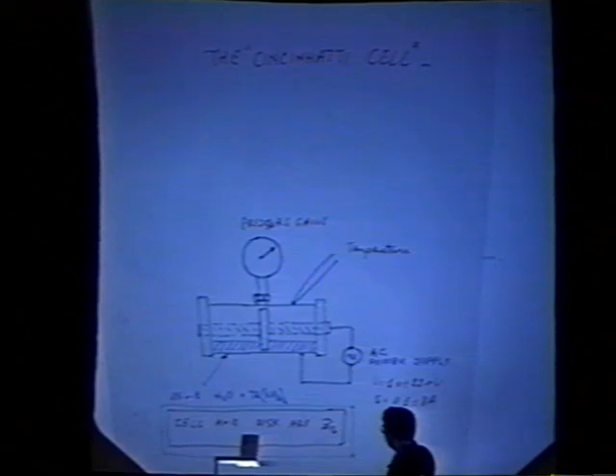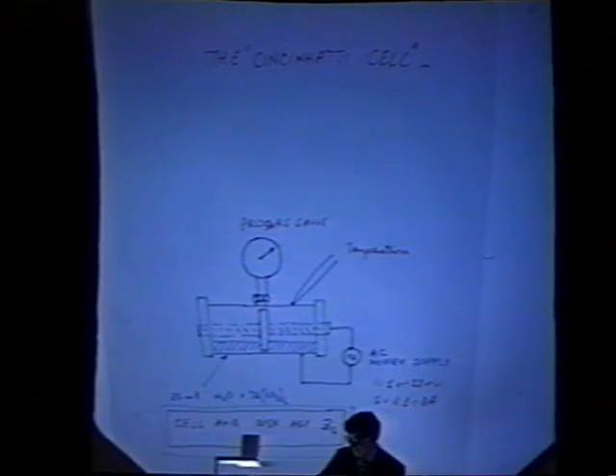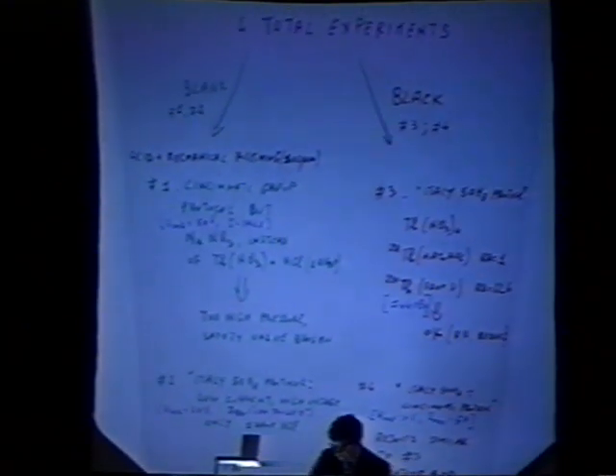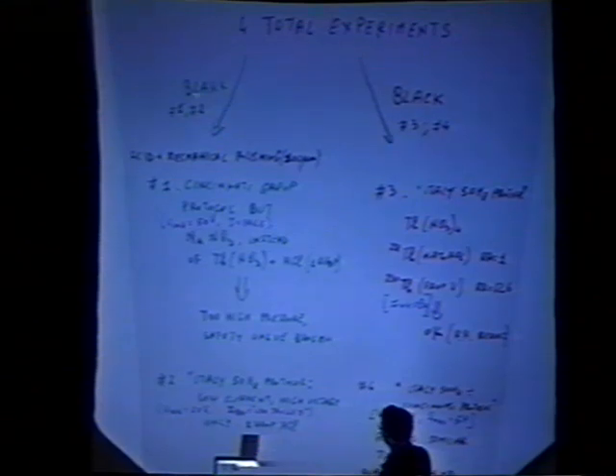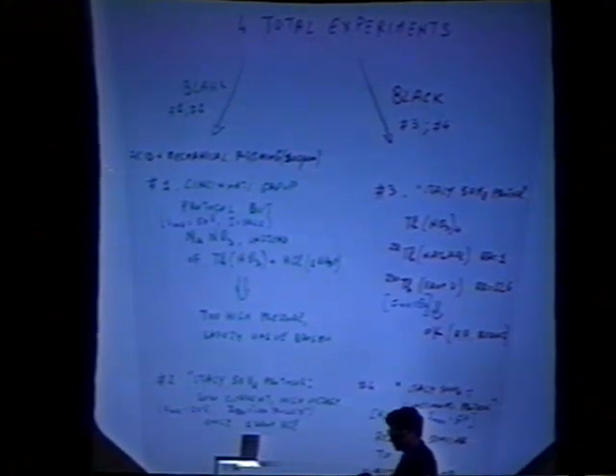According to the Cincinnati procedure, we used 25 milliliters. The solution is about 1/3 of the volume of the full cell. We made in total 4 experiments: 2 blank experiments to be confident with this kind of device, and 2 to check for thorium transmutation, if any. So the cell before operation was cleaned strongly with acid, acetone and so on, and to be more sure, because of the property of thorium to attach to the surface, mechanically polished by 100 microns.